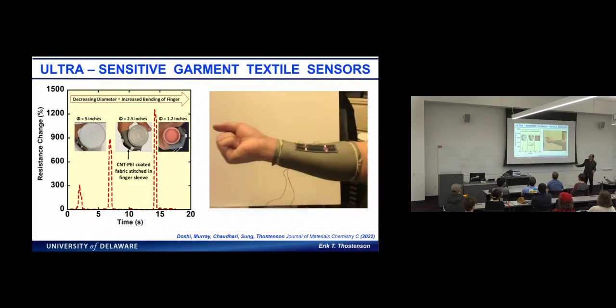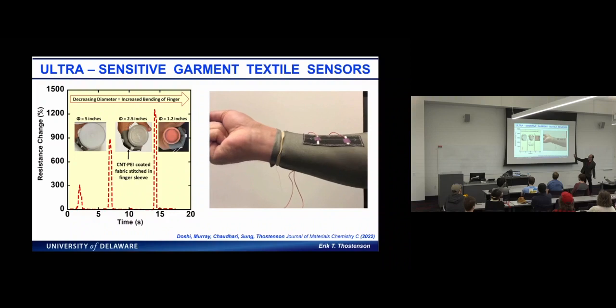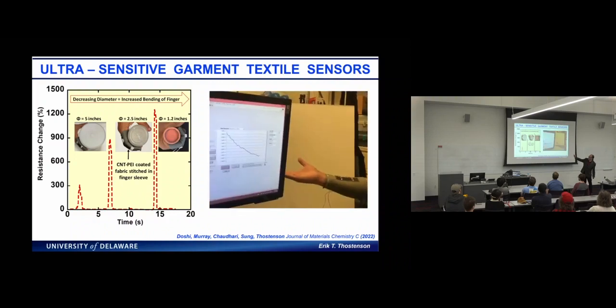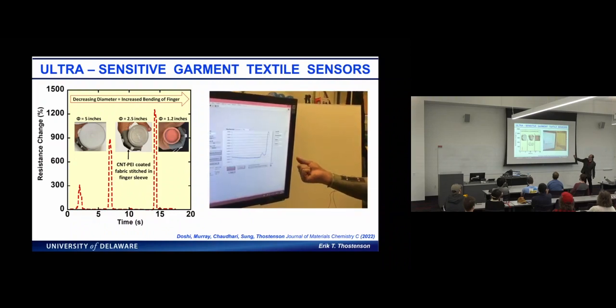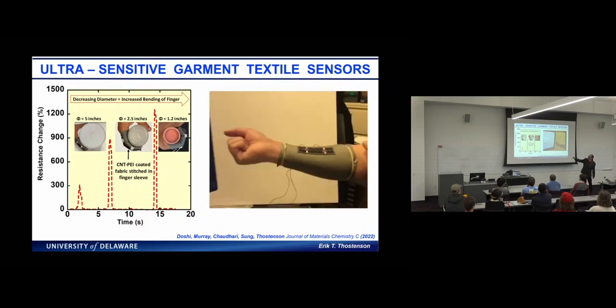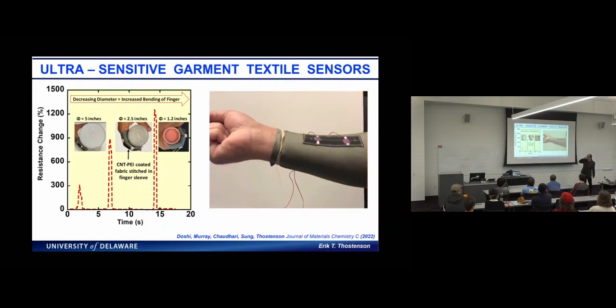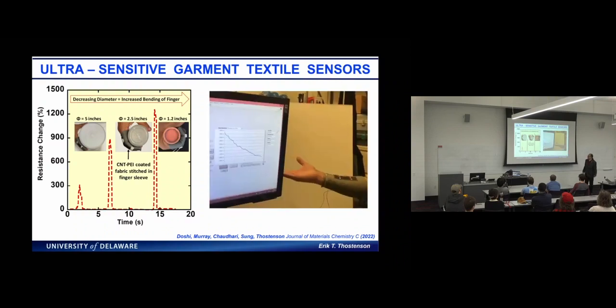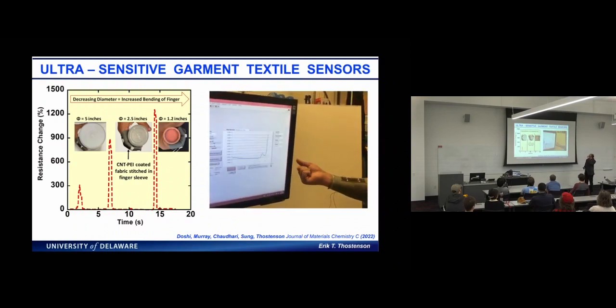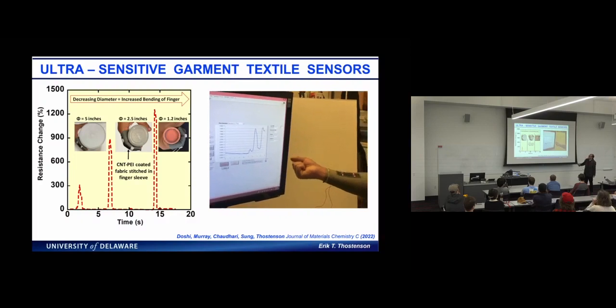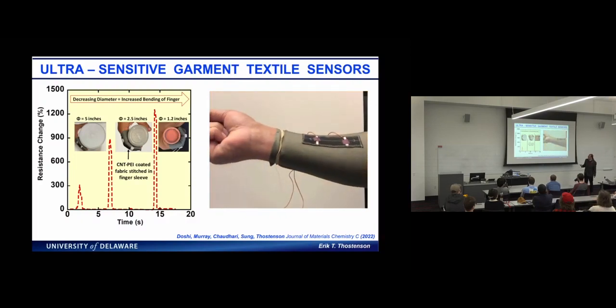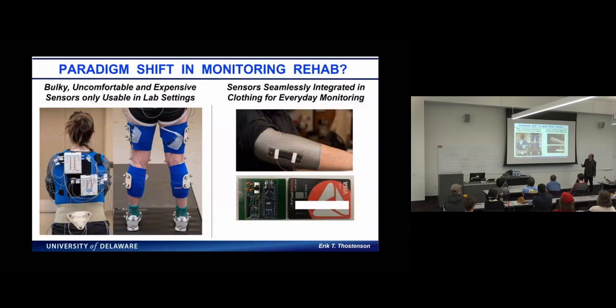So the idea here is gripping different radius curvature items, and we still see a very, very large change, up to over 1,000% change in the electrical conductivity, or resistivity in this case. You can see that response just to that very delicate motion. And so this is our idea to take it out of the lab. And we have a new project where hopefully we're going to be doing a lot more validation with human subjects.